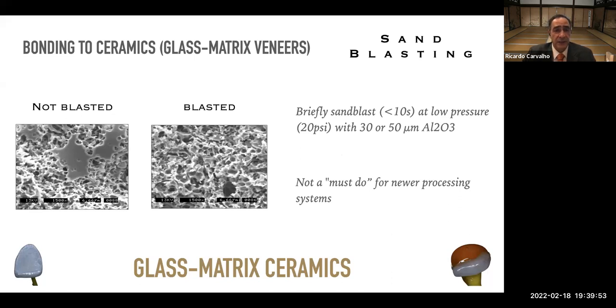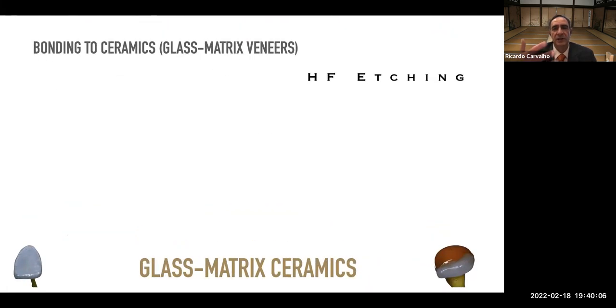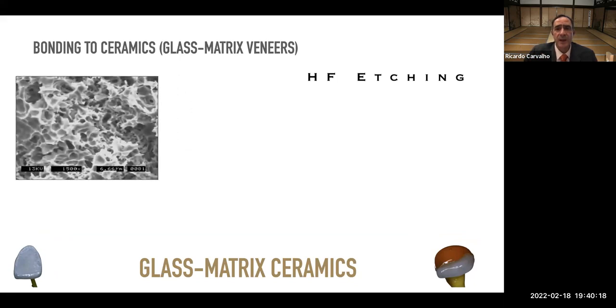But as we know nowadays, with all these CAD/CAM milled veneers, or even 3D printed as it's coming, usually the sandblasting step is not necessary because the ceramic surface already comes clean from these milling machines. There are no residues. Hydrofluoric acid etching, however, is a little bit more important, if you will, for the bonding.